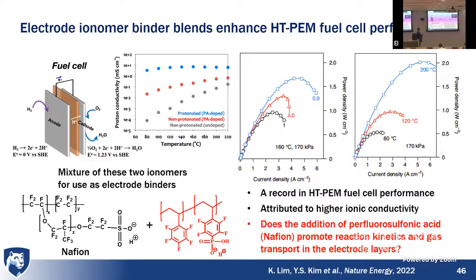And then if we mix these two and we look at different temperatures, 80, 120, and 200 degrees C, they were able to get 2 watts per centimeter squared. And this was a record in HT-PEM fuel cell performance. And this was really attributed to higher ionic conductivity. But we think this is not just ionic conductivity. We think this is also due to reaction kinetics and gas transport in the electrode layers.